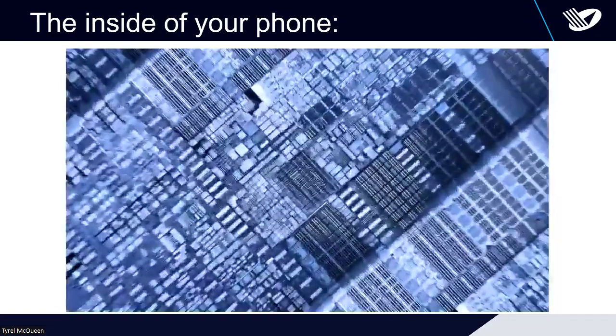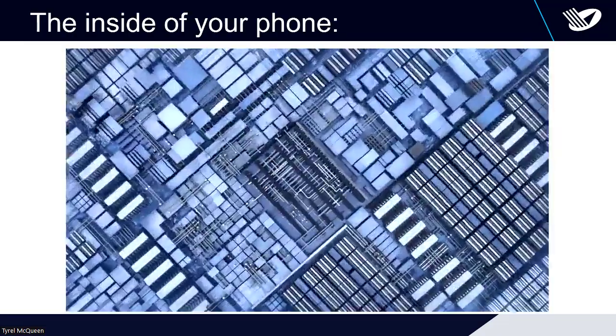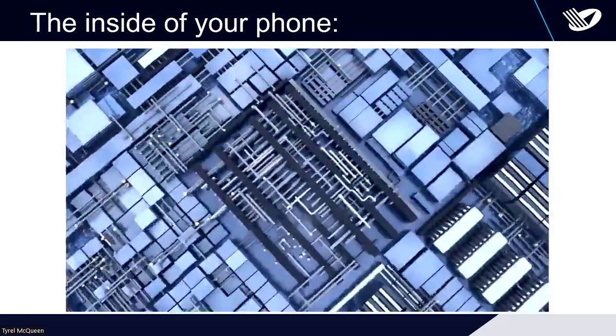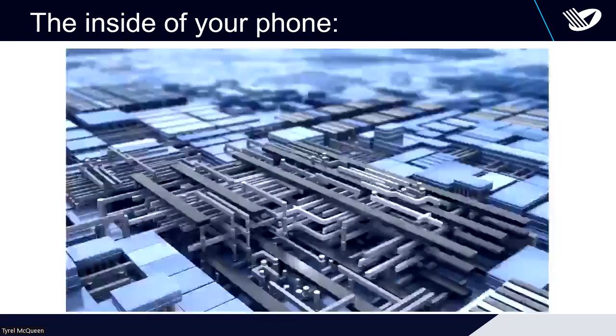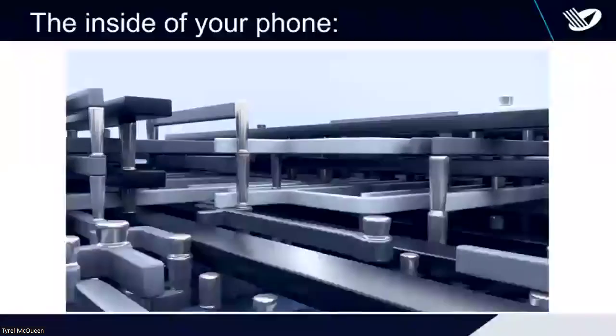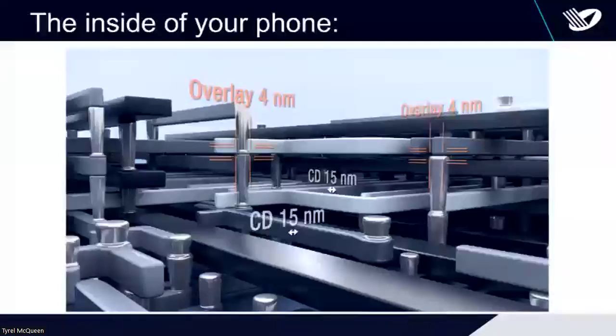This is here really a whole three-dimensional architecture of many different structures. At some point, we get the 3D view. Here we go, of the different transistors that are all interconnected with copper wires. And the typical dimensions, by now maybe even a bit smaller than that, are critical dimensions of what is indicated here, 15 nanometers. So the critical dimension is the smallest size, the smallest width of any of the features. And then the overlay, that's even smaller. That's how accurately they are positioned on top of each other. So that's about 4 nanometers.